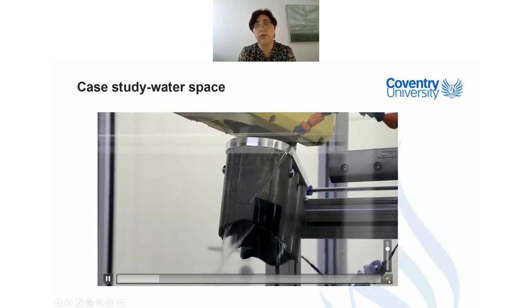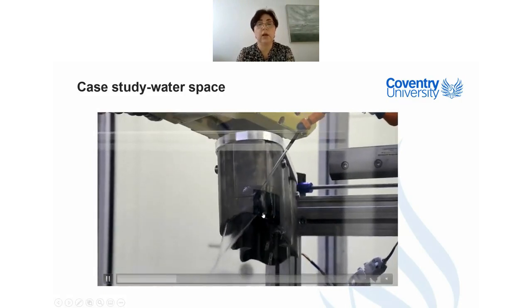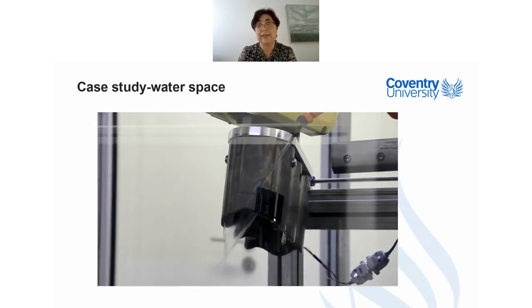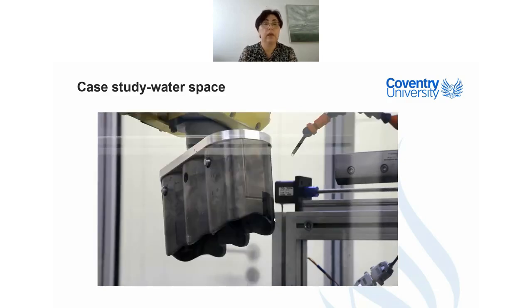Okay, and the results: you see a tool before treatment was able to work for something like 5,000 strokes, and there was a loss of material of 0.73 millimeters. While after laser shock peening, we were able to increase the number of strokes by more than 2.5 times, I would say, and we slightly reduced the material loss.